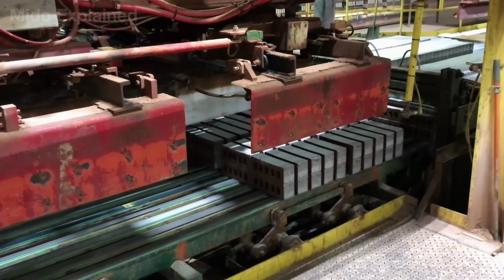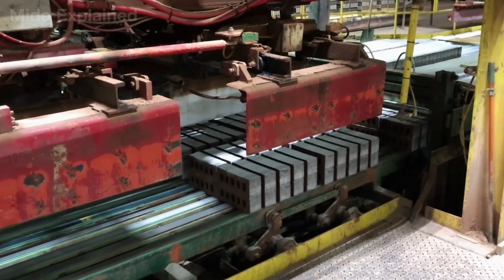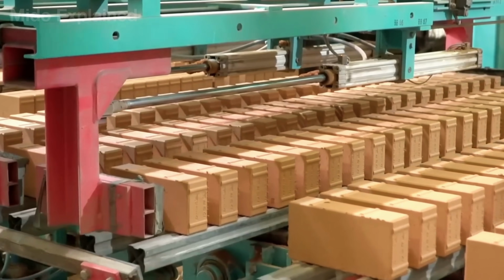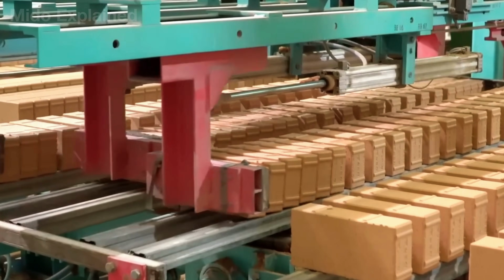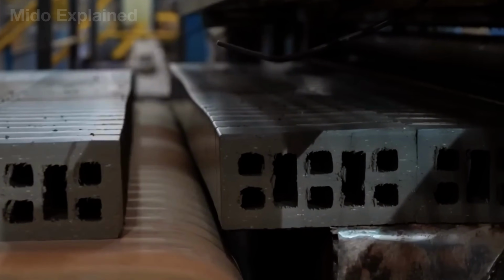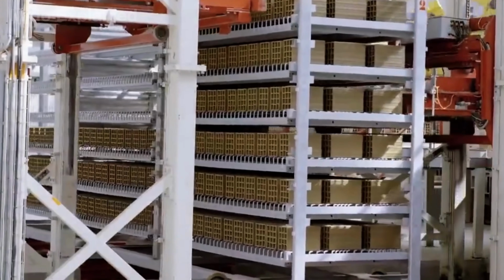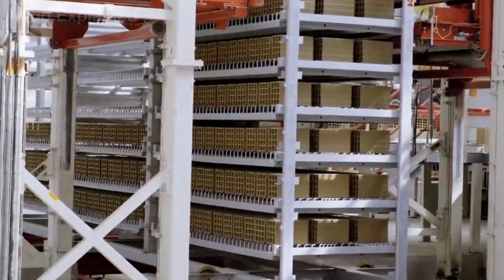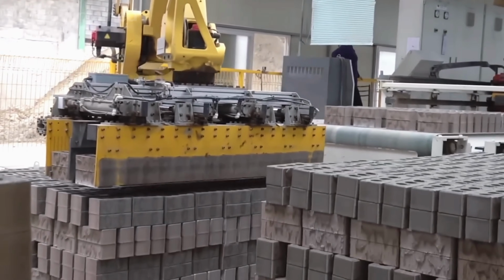If the water evaporates too quickly, internal pressure can build up and cause the bricks to crack or break before they are fired. On the other hand, if the bricks are not dried enough, the remaining moisture can also damage them when they reach high temperatures in the kiln.